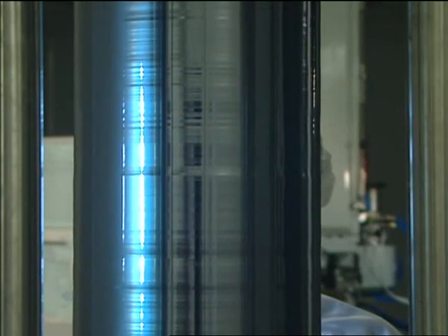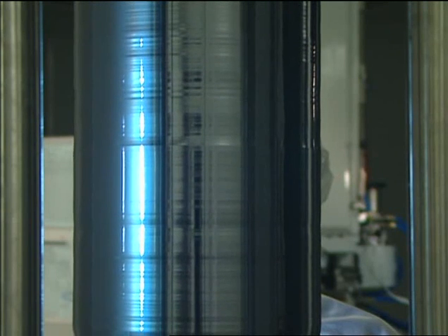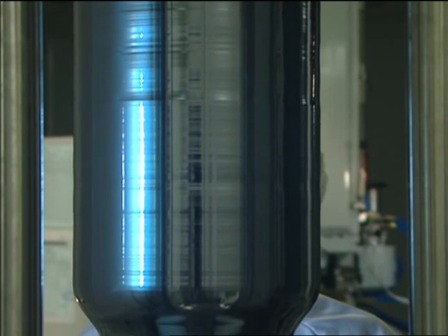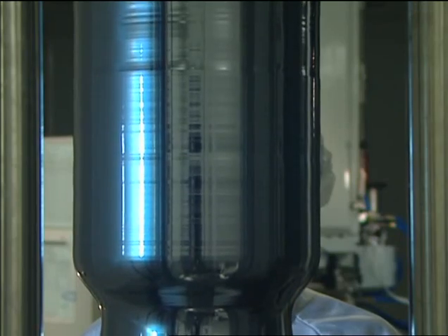The final product is a monocrystalline silicon rod of highest purity. This means the rod has only one impurity atom for every 10 million silicon atoms.